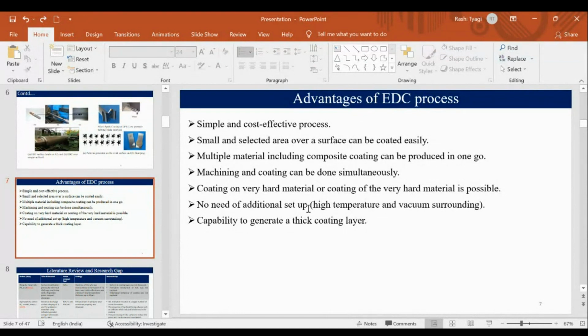No need of additional setup. Sometimes some machines need additional setup such as vacuum. They need a vacuum to deposit the coating. But in this process, you don't need a vacuum to deposit the coating. High temperature and high vacuum surrounding is not needed. Capability to generate a thick coating layer. It means you can generate any thickness of coating layer.